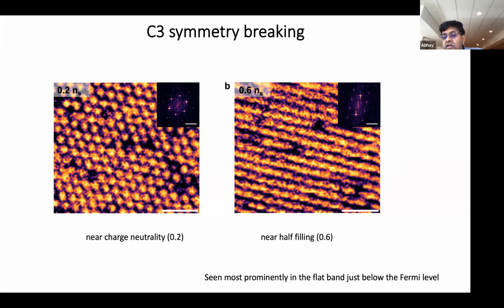What we would love to be able to see is domains of this nematic phase where it changes direction, like we could see in the pnictides. So far, we've been unable to see domains in these samples. Do you have an idea why it prefers one particular direction? Because if it's threefold rotationally symmetric, you should expect all three directions to be equivalent, right? Yes, but it's a spontaneously broken symmetry. So it picks one of the three directions, and one would expect that if one has an infinitely large sample with no external strain, you should see all three domains. But we've never managed to see the domain structure in this.